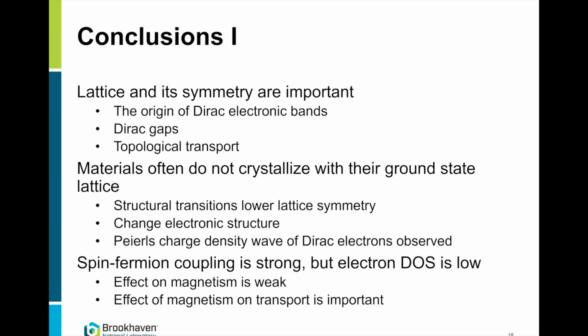So I'll do the intermediate conclusion. What I've shown so far is that the lattice symmetry, which determines the origin of Dirac electronic bands, is not necessarily what materials crystallize with. I mean, you can have this Peierls distortion with changes. This challenges DFT predictions, of course, because you do a DFT calculation for ytterbium-manganese diantimonide, but whether you calculate it in the high temperature phase or in the low temperature phase, you will have different results.